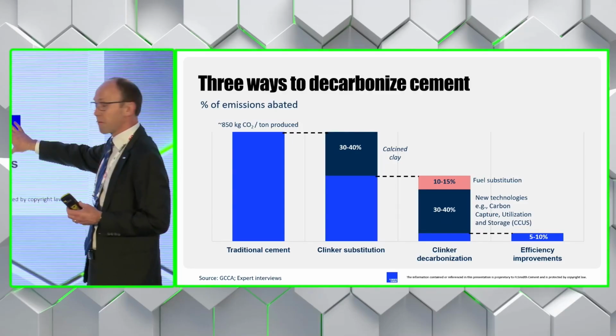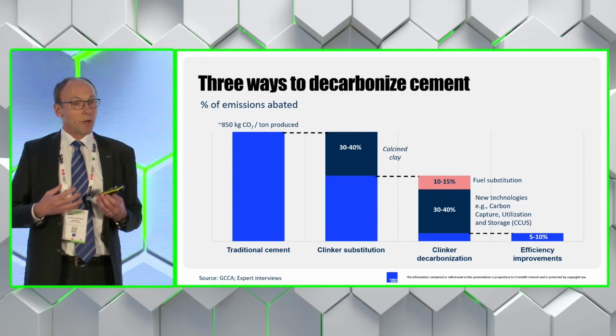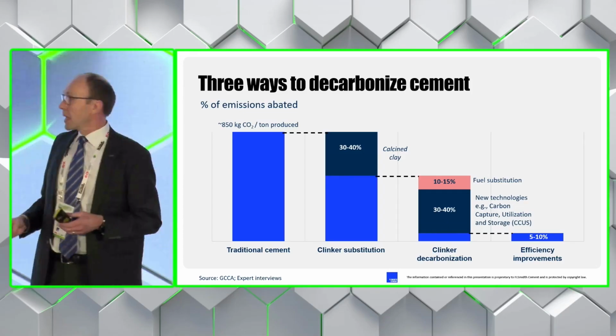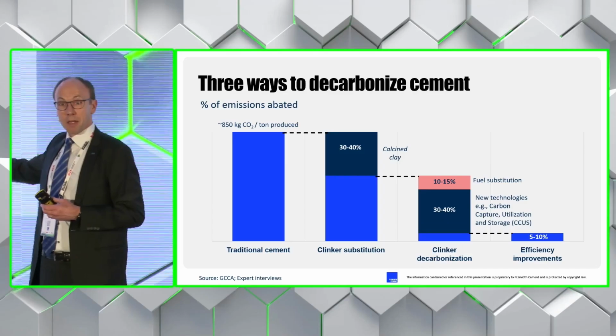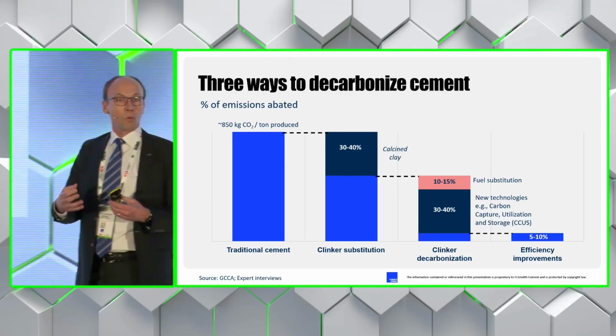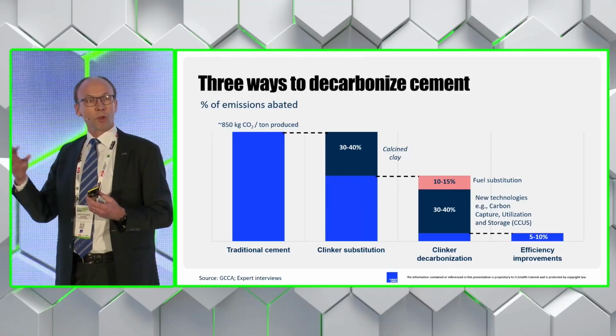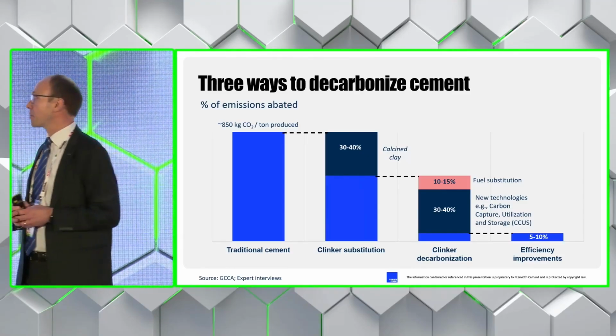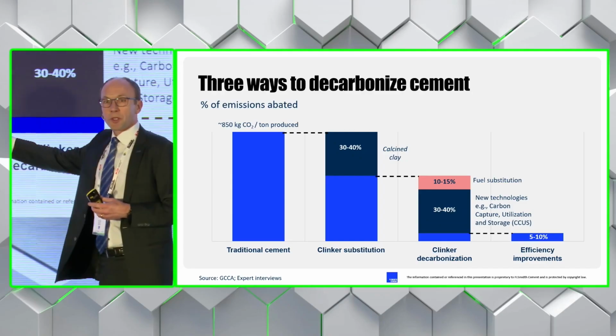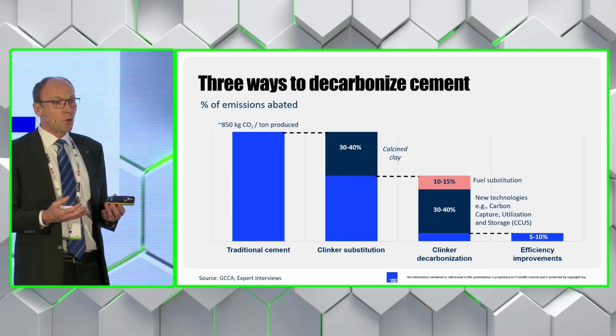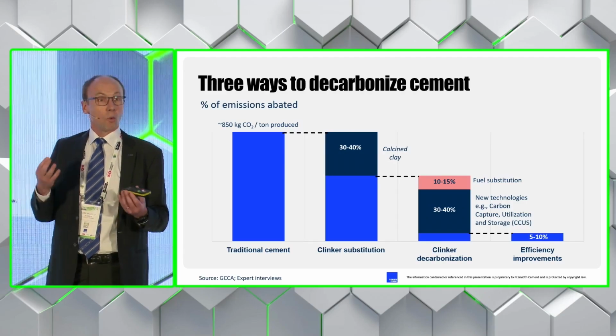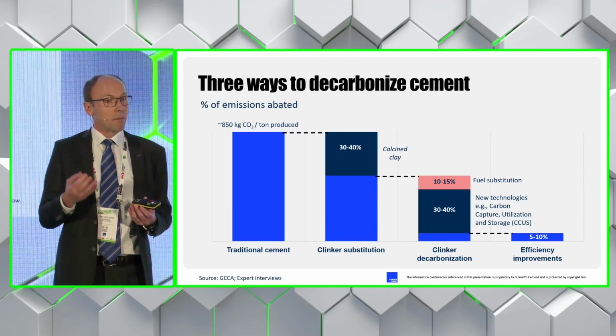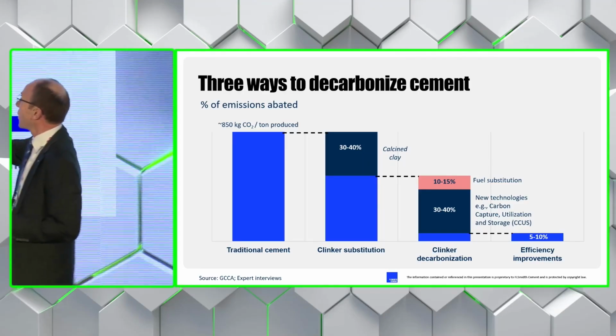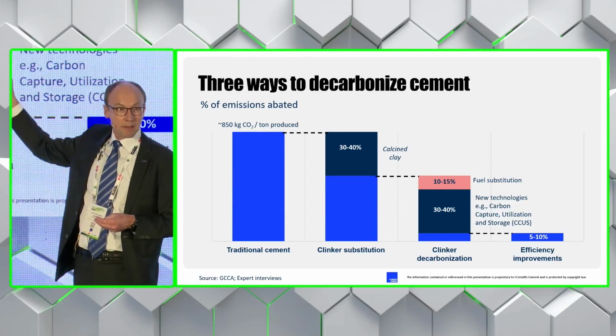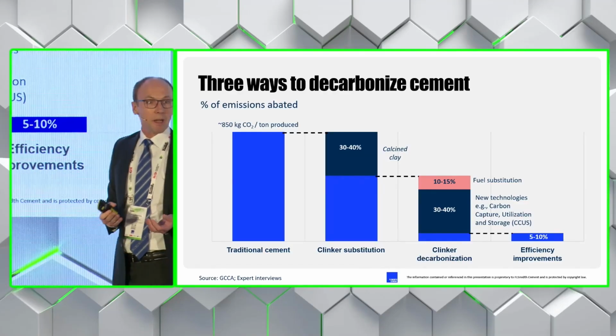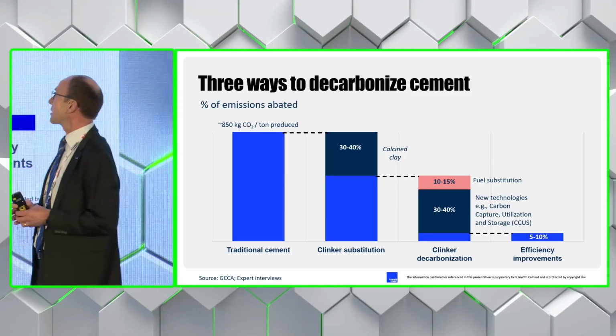Of course, you could argue that the efficiency improvements over here are also really effective in reducing emissions. But there's a limited scope in these efficiency improvements. We've already gotten far with getting a high energy efficiency, both thermal energy and electrical energy. If we go to clinker substitution here, traditionally we'd substitute clinker using natural pozzolans or waste materials like fly ash or slag. But now, as we've heard, there's an increasing focus on using calcined clay, and so artificially producing calcined clay as a supplementary cementitious material.